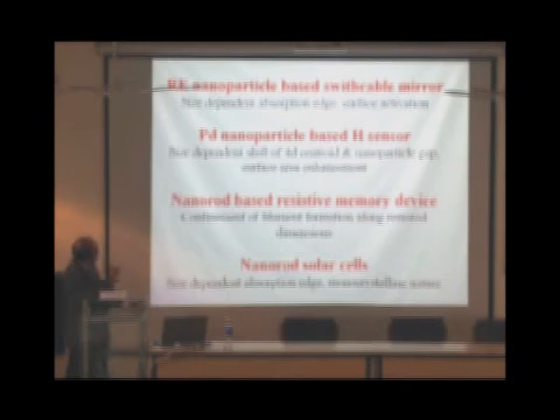So I would like to conclude my talk by stating that I took 4 examples. In the first example, nanoparticle based switchable mirrors, we saw that size-dependent change in the absorption edge and surface activation of hydrogen molecules improve the properties of this material. In palladium nanoparticle-based hydrogen sensors, size-dependent shift of the palladium 4d centroid, nanoparticle gaps, and surface area enhancement improve the properties of the sensor and change the saturation response to a pulse response for hydrogen. In nanorod-based resistive memory devices, confinement of the filament formation process along nanorod dimensions helps, and in nanorod solar cells, the size-dependent absorption edge and monocrystalline nature can improve the performance of the solar cell.